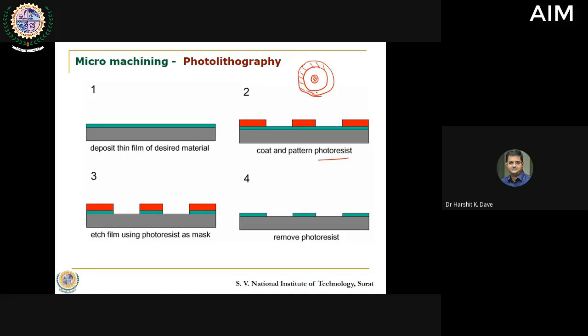This is the cover. So if I take a cross section over here, I see this one. This is what I see over here. This is what is visible to us. Now what we do is, after coating this with a photoresist, we use this as a mask and pass some sort of laser energy, or maybe some UV light, and we burn the material. So nothing happens to this part, but the part over here is burnt. Okay, so now it is etched, it is removed. First we deposited, and now we are removing this.